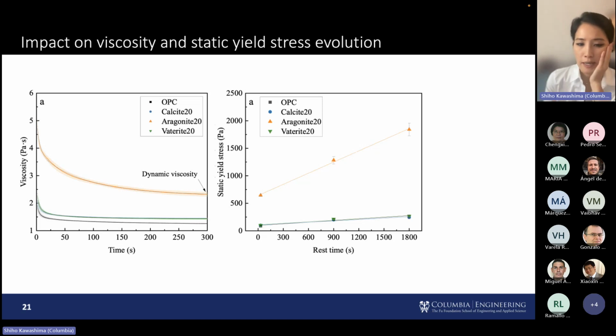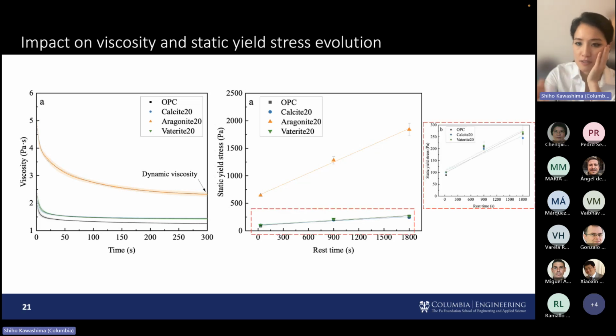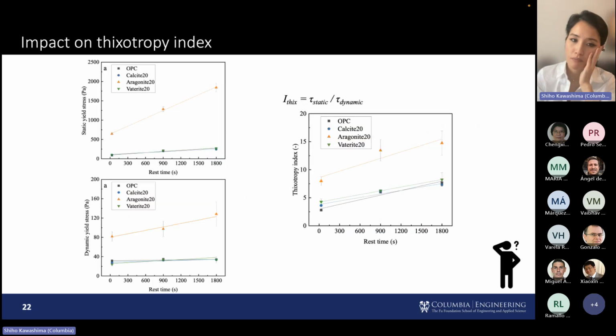We also measured that, and it was an order of magnitude higher. So there's something where the aragonite is impacting the rheology very differently. And this is just to focus in on the calcite and vaterite because it gets a little squashed. But really no significant change on static yield stress evolution compared to OPC with no calcium carbonate replacement.